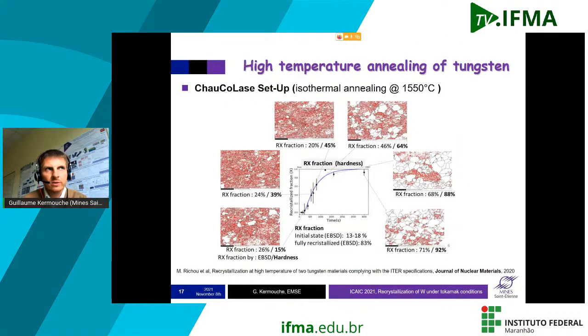Let's now present some results with this setup. Here you can see a recrystallization kinetics at high temperature, 1550 degrees Celsius, on a tungsten that can be used classically for ITER. You can see here the evolution of the recrystallized fraction, that means the ratio between the white area here and the whole area of the microstructure. And you can see that the recrystallized fraction increases with time until it reaches 100%. We have a small discrepancy between the recrystallized fraction measured from microstructural measurement and from hardness measurement. But it comes from the fact that with hardness measurement, you also have to consider the competition with recovery, which we don't see with microstructural measurement.